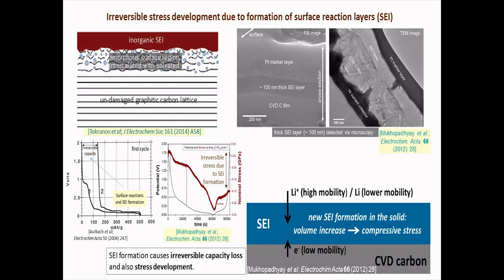Another aspect which I have not mentioned so far, which causes stress development, is formation of a passivation layer on top. When a bare electrode is exposed to the electrolyte, during the initial stages of cycling, a passivation layer forms on top of the electrode. This passivation layer is known as the solid electrolyte interface, and when it forms, it protects the electrode from further reaction with the electrolyte. However, it also leads to a lot of irreversible capacity loss, primarily in the first few cycles, and as we found out, it also leads to development of huge compressive stress which does not get reverted back.